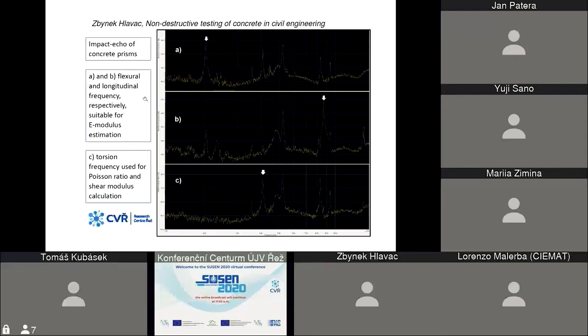So here you can see 3 cases. In the top screen you see picture A, and we are trying to force the oscillation in flexion. Usually the peak on the spectrogram is the highest. So you can see the dependence of amplitude on frequency here. If we come to letter B, we see the longitudinal frequency, mostly because the velocity of longitudinal waves is the highest. So we usually start with this frequency measurement.